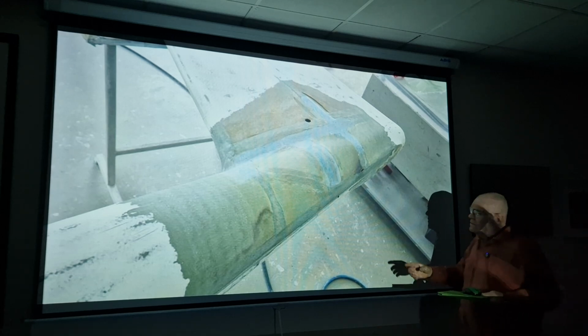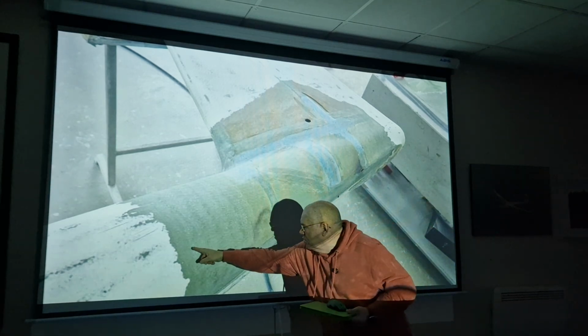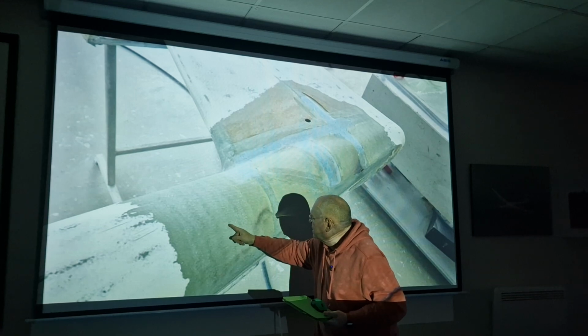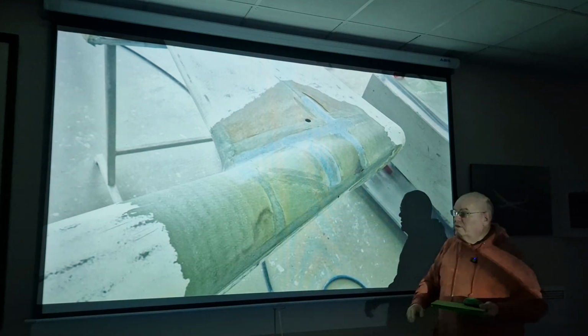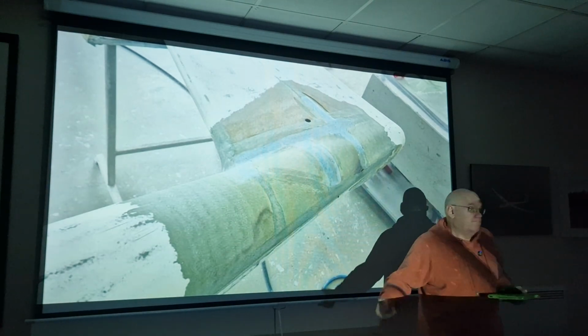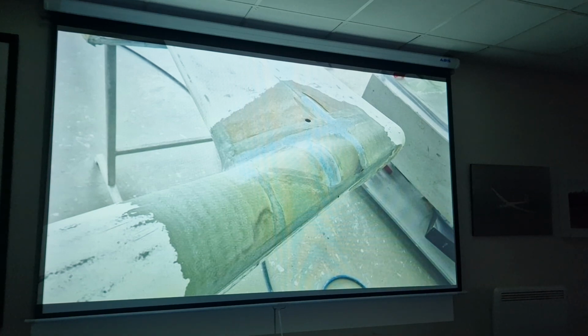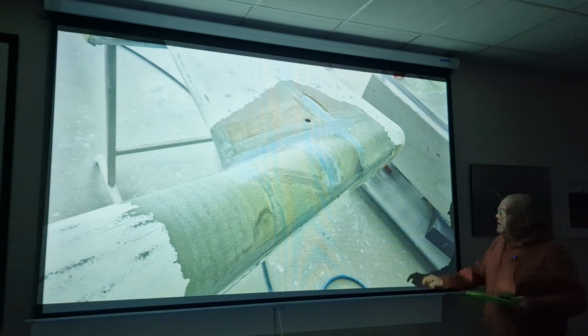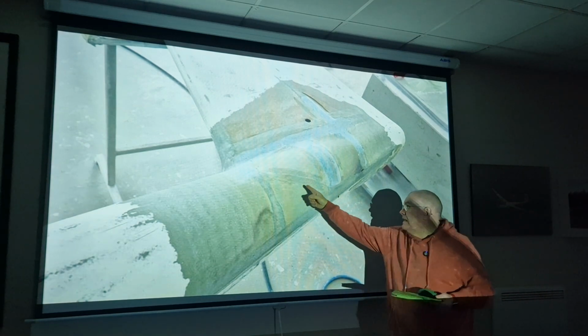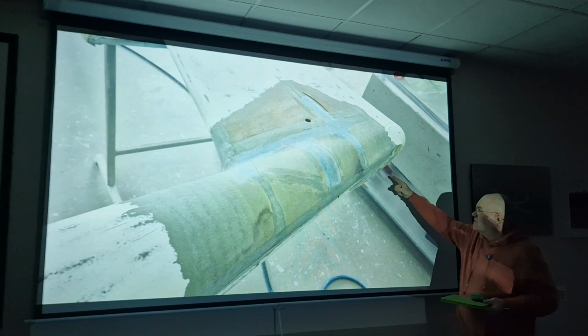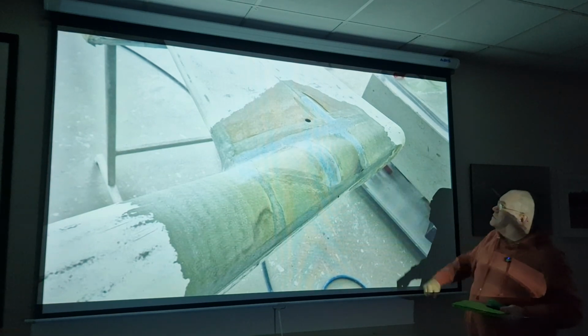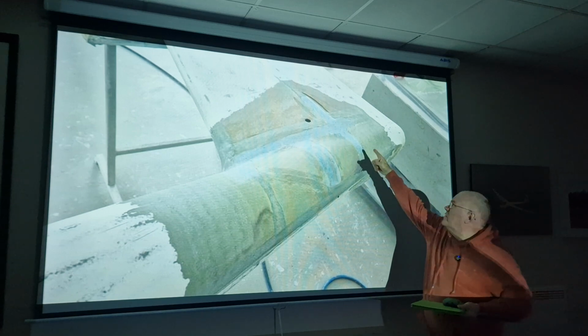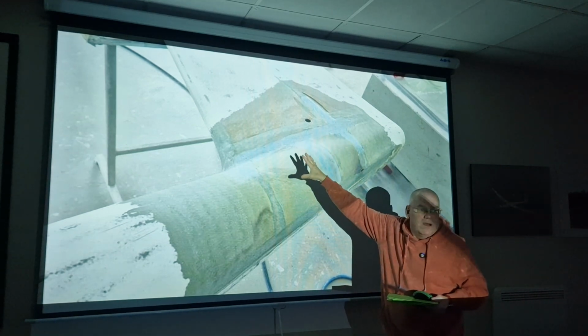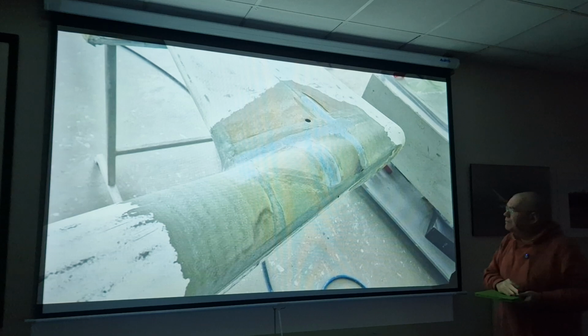This is the back end of a Discus we were repairing a long time ago. Exactly the same glass fibre, but they've doubled the layers: 1, 2, 3, 4, 5, 6, 7, 8. Because all you do is just slap more layers in the mould. Simple as that. Once you've got a mould, it's a very, very simple method. In this case, we actually put a glass fibre back in here, superglued in place. This was a really easy one. It's one of these rare Discuses without a tail wheel in it. Over these areas where there's foam core, we actually vacuum it down as well. We put a vacuum bag over that bit.